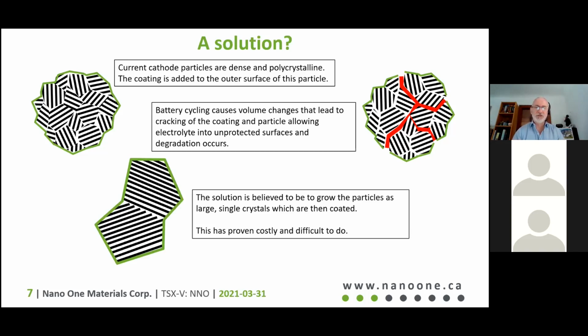A solution to that that's been developed in the industry is to grow very large single crystals, or quite often there's two or three in a big lump, and then put the coating around the big crystals. They expand and contract, but the particle doesn't fracture so much. But growing these big crystals is costly. It takes a long time to grow them, and it is quite often difficult to produce high quality material with these single crystals.